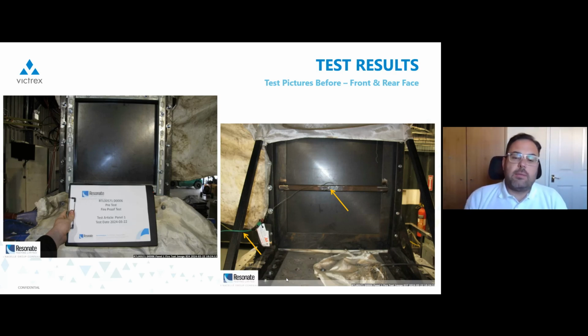What you see is a cable. That cable is one of the thermocouples that we attach at the back. As you can imagine, because the temperature of the panels will go quite high, trying to stick thermocouples on the rear face is almost impossible. So the test house that we used have a way of having the thermocouple touching the back of the panel, exactly opposite the center of the burner. Where you see the central yellow arrow, there is a spring that pushes the thermocouple against the panel so as to make a measurement. So this is the picture.